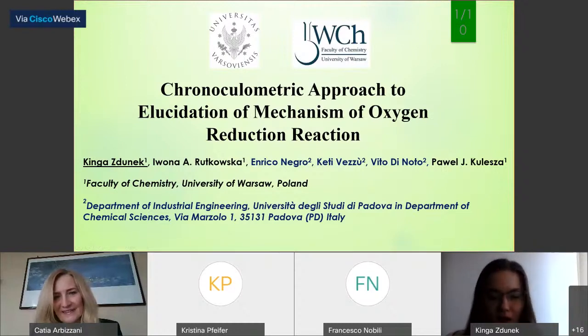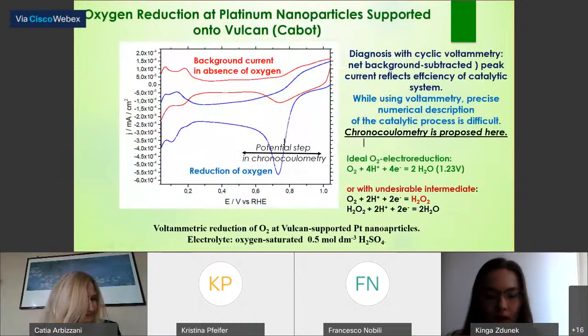Today I will talk about a chronocoulometric approach to elucidation of the mechanism of the oxygen reduction reaction. On this slide, you can see voltammetric reduction of oxygen at Vulcan-supported platinum nanoparticles. The red line presents background current in the absence of oxygen, and the blue line presents reduction of oxygen. For complete electroreduction of oxygen, we need 4 electrons, and we want to decrease the formation of hydrogen peroxide.